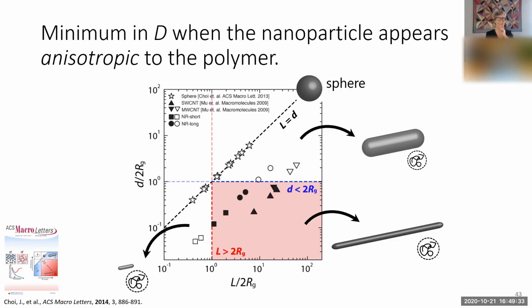Okay, so my intuitive picture is you have this really skinny needle, and I guess I'll take one step back. On the next slide, you're measuring polymer diffusion coefficient, but what about the nanorod diffusion coefficient, right? Your polymers are moving, but if you have a particle that can potentially move faster than another particle, is that going to have some effect? Right, that's a great point. I forgot to mention that too. When we're looking at polymer diffusion, we are doing it at temperatures and with large enough particles that the polymer is diffusing about 100 times faster than the particle. So when we're talking about polymer diffusion, the particles are effectively immobile.